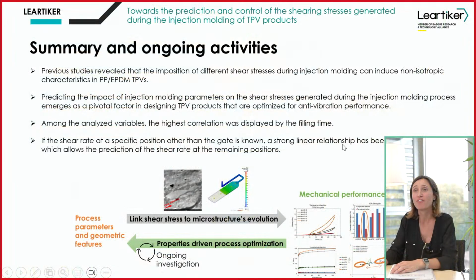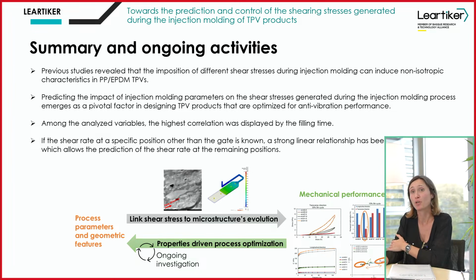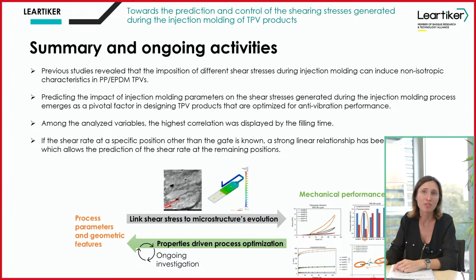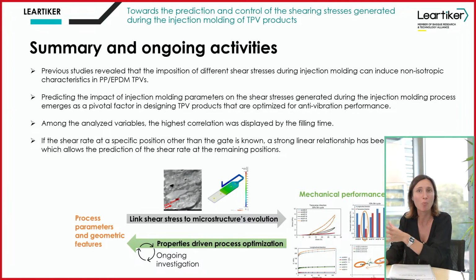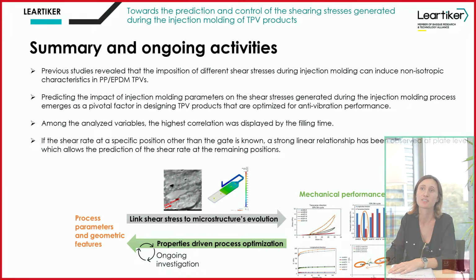And now we are working on how all this affects the mechanical performance. So in these plates that have been injection molded, we are doing different quasi-static and dynamic mechanical analysis trials to, at the end, link the process parameters with the mechanical performance, and to do a properties-driven process and component optimization, to be able to finally tune the key parameters that govern the performance of anti-vibration components based on TPE materials.